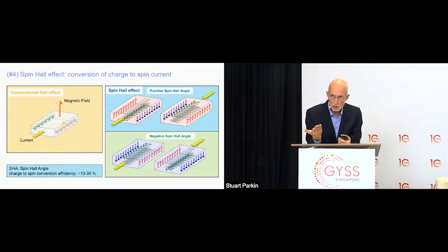But it turns out in some materials, without any magnetic field and without any magnetization, you pass a charge current here into, let's say, platinum, and you will generate a current of spin polarized electrons that flows in a clockwise or anti-clockwise direction around the current. And this spin polarized current can be extracted from the surface into a magnetic material to provide spin orbit torques.